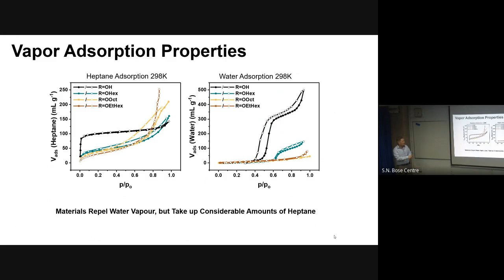But the others, they are basically swelling with the heptane. So they take up a decent amount, but with increasing pressure, more and more heptane is taken up, and it's also dissolved. The side chains interact very well with the longer elements. Is this absorption because of the space that you have in the framework? Yes, on the one hand, the accessible space in the framework, but also the interaction sites.